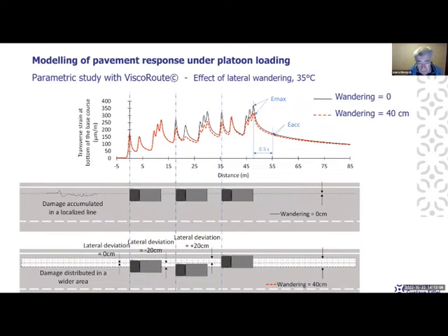We studied the effect of the lateral wandering on the strains. So we compared first a case where the trucks were perfectly aligned with zero lateral wandering, and then where the three trucks were misaligned transversally with a lateral wandering of plus 20 centimeters and minus 20 centimeters.